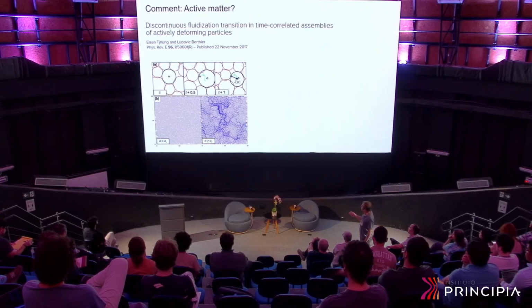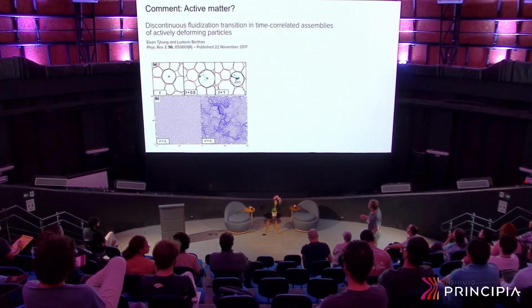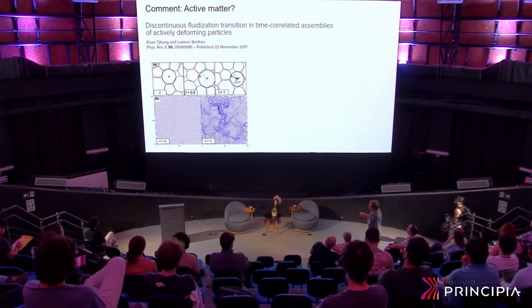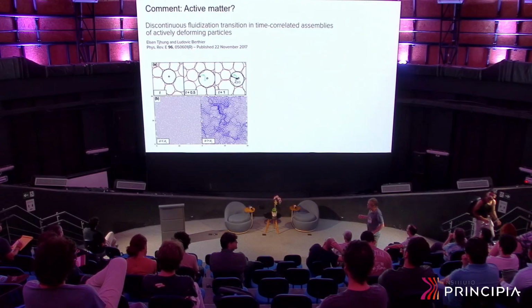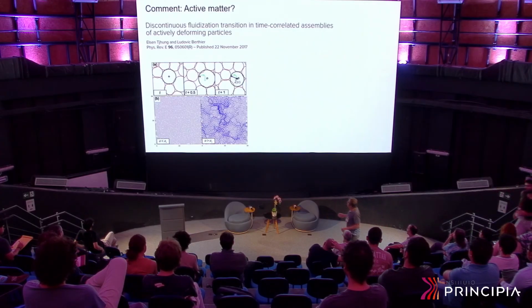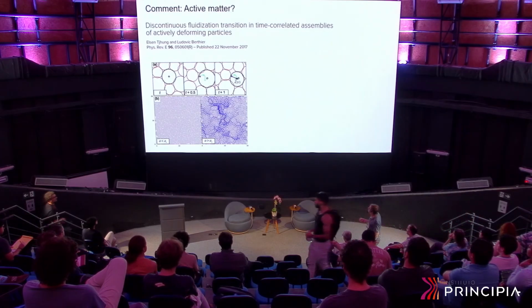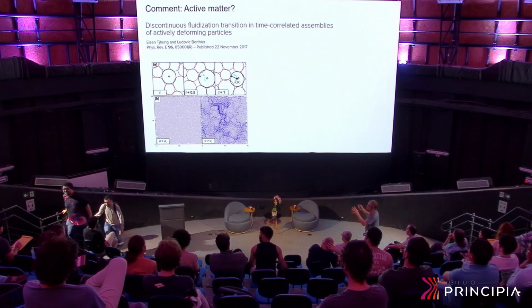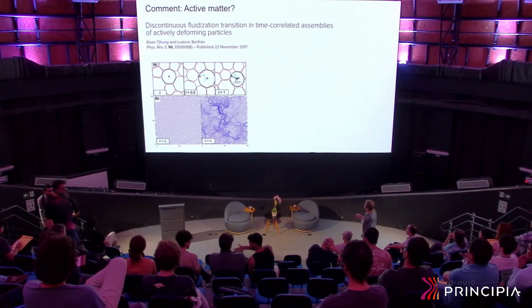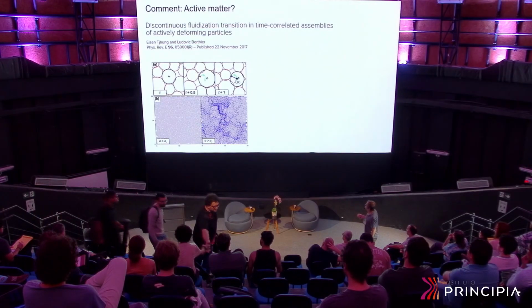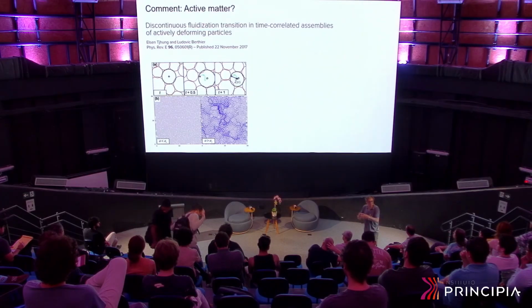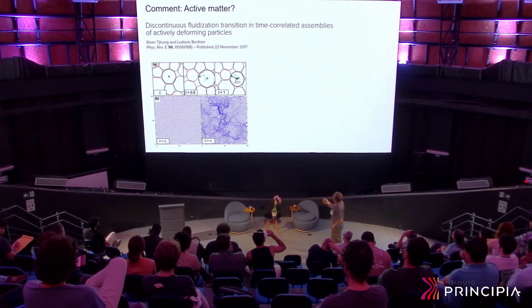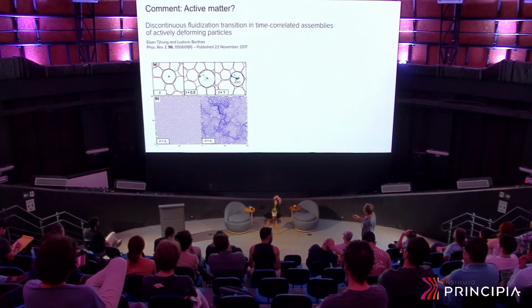But it happens, these people show, that after a cycle of variation of the radius, this particle can probably not turn back to the original position, but turn to another position. In fact, if the amplitude of the oscillation of the radius is small, typically all particles return to their original position, so the material continues to be a solid. But if the amplitude of the oscillation is larger than some critical value, then after a cycle the particles move to another position, and if you repeat this again and again, this continues to change over time. So this was called a kind of fluidization transition induced by the change of the size of the particles. For anybody interested, this is a nice paper.